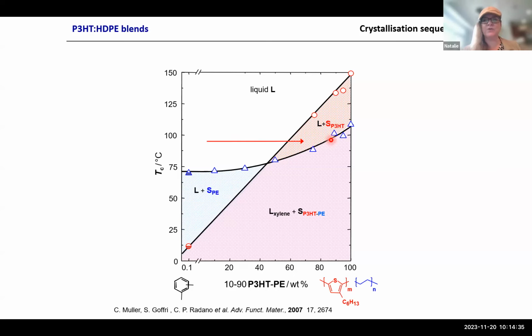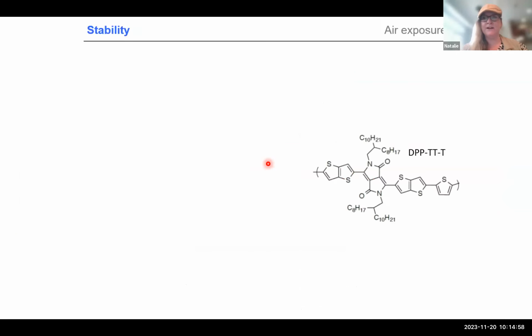And then once the polyethylene starts to crystallize, it forms fibrils. It really pushes these electronic pathways together. Ideally, of course, you would cast exactly at this temperature where both crystallize at the same temperature. That would guarantee you the finest phase separation. And I have to say, once you know how to process, it works for every system.